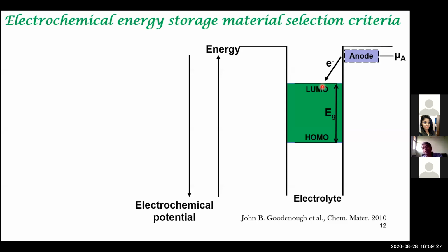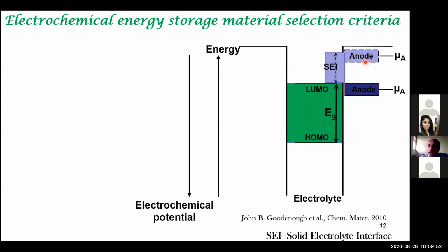Supposing you had an aqueous electrolyte in your lithium-ion battery. In a typical lithium-ion battery in your cell phone, you have non-aqueous systems, some organic electrolytes. Even for those organic electrolytes, the LUMO can be at a lower level compared to this level. So there is some decomposition that occurs, and then an insulating layer is formed, called the solid electrolyte interface, SEI. This is one of the mysteries. We are lucky to have the solid electrolyte interface, or else we cannot operate a lithium-ion battery.